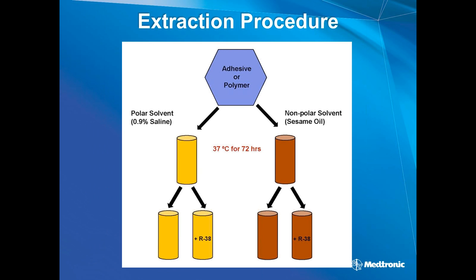We started with our materials, and then we made actually 4 separate extracts, and these ran at physiological temperatures, 37 degrees C, for 3 days, which is typical based on the ISO standards. And we used sesame oil and saline, and we made 4 different extracts in the end. And at the bottom, you see these cones, the yellow over here. This one is spiked with our lactic acid. This one is spiked with an appropriate amount of heptanoic acid, and then these are just plain. And so these are saved as controls, actually.